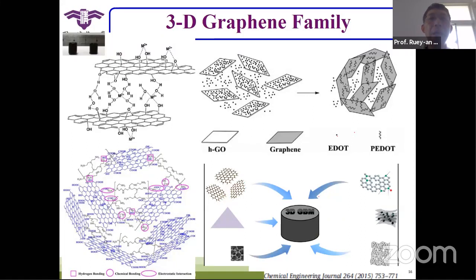And the other case is the three-dimensional graphene family. From the two-dimensional, since at the edge they have some functional groups, hydroxyl or carboxylic groups, they can link together. So we can try to add some metal ions to link them together, and the two-dimensional becomes three-dimensional. From the right-hand side here, you will always see that they have the two-dimensional frame, so they can keep the electrochemical property of reduced graphene oxide or the graphene family, but they have a lot of space inside.